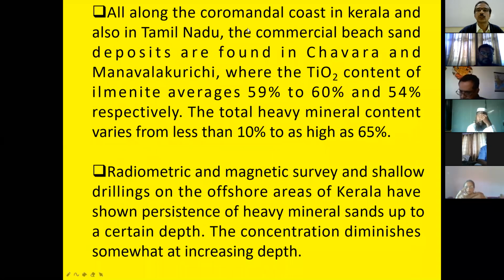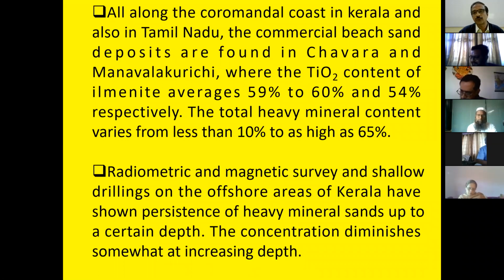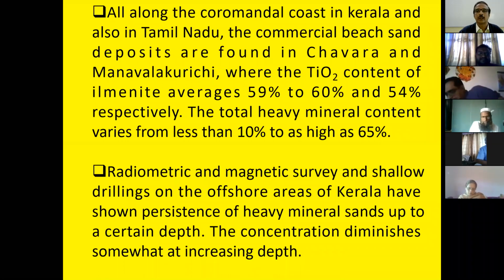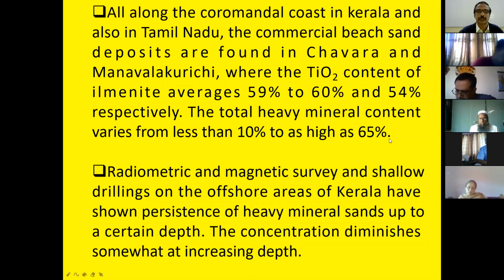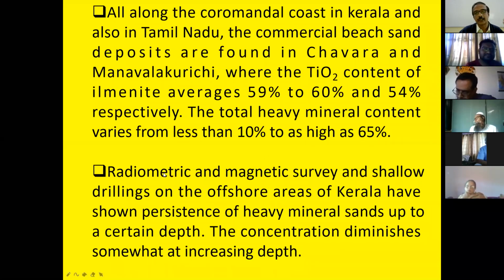So all along the coastal regions in Kerala and Tamil Nadu, commercial beach sands are found in Chavara and Manavalakurichi in Tamil Nadu. They all contain TiO2 varying from 59% to 60% and also 54%. The heavy mineral content also varies from less than 10% to as high as 65%. Surveys have been done, a radiometric survey, that means taking a Geiger-Müller counter, they have surveyed these areas, and they have done a magnetic survey.